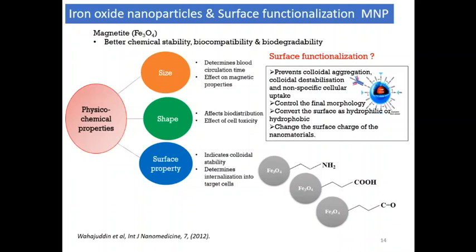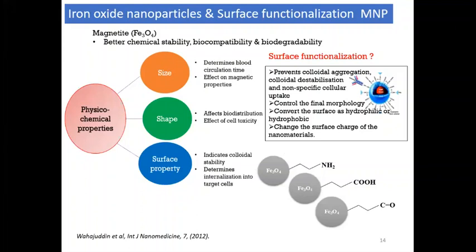Because of the electrostatic stability mechanism or the steric stability mechanism, we can control the colloidal stability of the nanomaterials. Surface functionalization prevents colloidal aggregation. The nanoparticles should not aggregate, and it controls the final morphology. You can control the morphology of the nanomaterials by using different functionalization techniques, and convert the surface to hydrophilic. Sometimes a hydrophobic surfactant is used to disperse the material, and the surface ligand has to be changed through certain techniques to get hydrophilic functionalization, and it also changes the surface charge of the nanomaterials. So to optimize better colloidal stability, we need to functionalize with different types of organic molecules.